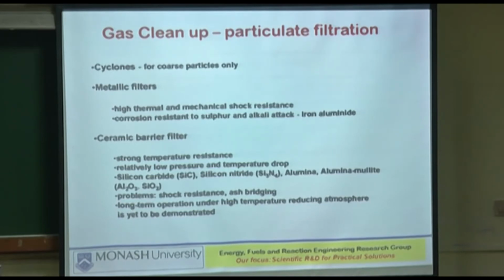unless you have cooled it down before the metallic filter, and the sticky hydroxides, etc. So the chlorides and the sulfides at those temperatures, and also because of the pressure, will give rise to stress corrosion of the metal filters.